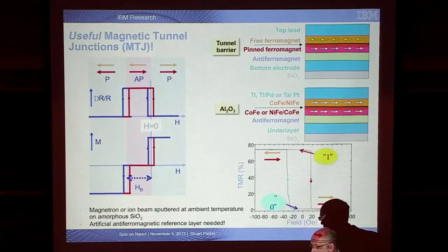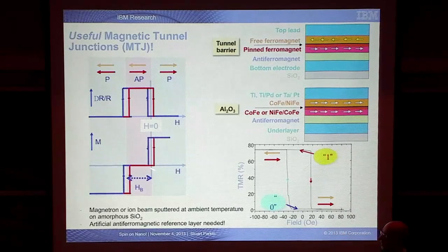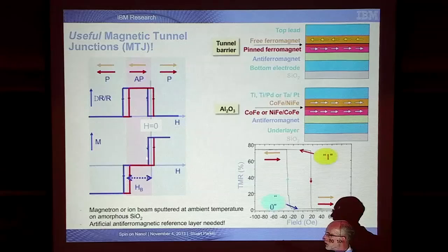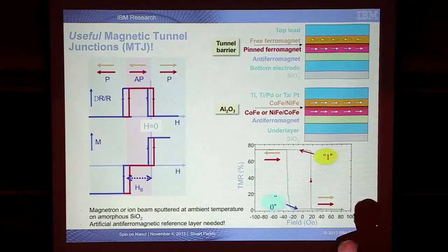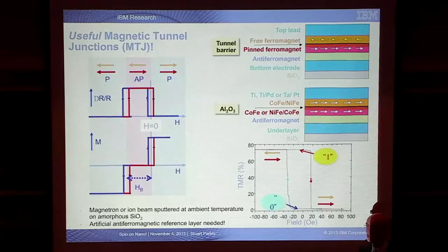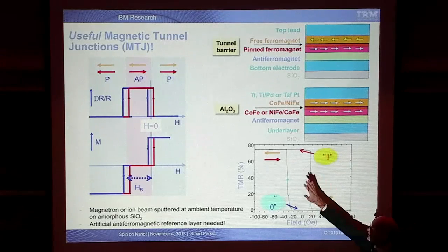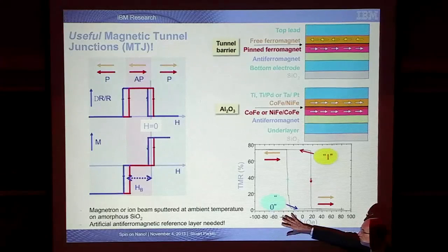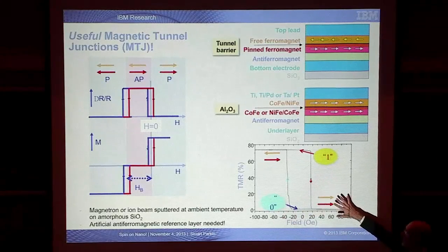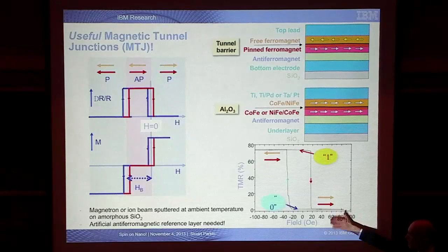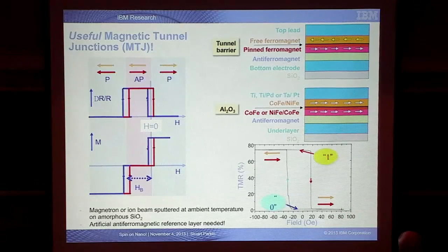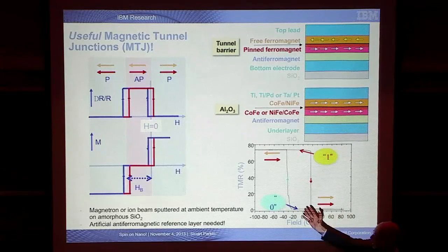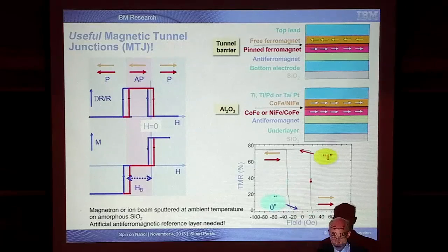And this can be used to set the direction of the magnetization of one of these layers. So the hysteresis loop is now no longer centered at zero field. It's centered at what is often called the exchange bias field. What it really means is, for all useful fields we will apply, the magnetic moment of one of these layers is essentially insensitive to field, and only the other magnetic moment responds. So as a function of magnetic field, the resistance shows this beautiful hysteresis curve. These are relatively small fields, about 100 times the Earth's magnetic field. At higher magnetic fields, the moments are parallel, the tunneling current is much higher, and the resistance is low. And when we change the orientation of one magnetic layer, the resistance is increased.